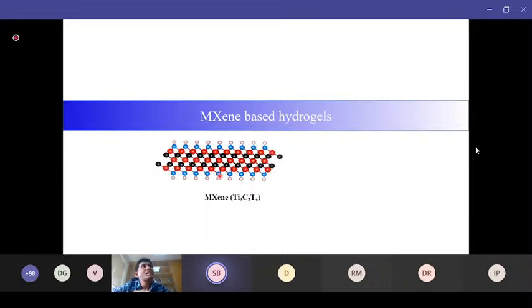But they can give a similar effect to the graphene in the sense that they have good EDLC-type, electrical double layer type capacitance, because they have a high surface area. And also, due to the presence of functional groups, those functional groups can give rise to redox activity, the pseudocapacitance. So as a result, in this material we have both performances. We can get the EDLC type like graphene, and the pseudocapacitive type like polyaniline within the same material. So that's why this one is very important.